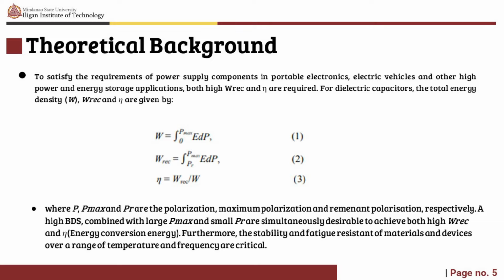However, with any given multi-layer, short-circuit pathways can emerge between low resistivity regions as layer thickness decreases, thereby decreasing BDS. The caveat, therefore, which must be applied to the Gerson and Marshall relationship is that BDS will only increase if low resistivity pathways are eliminated. That is, the materials have a high resistivity and are electrically homogeneous.